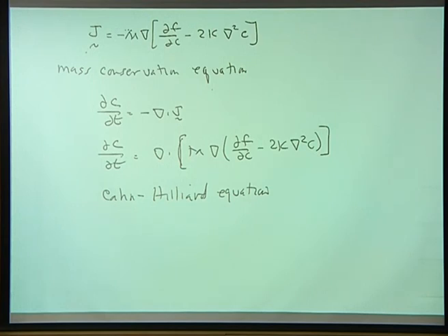So it involves the compositions that you get from the free energies. And here's the connection to thermodynamics. I give you a free energy function. It can be something that you get from a CALPHAD fit, for example. A CALPHAD free energy function is a function of composition for a particular system of interest. And if you know what the gradient energy coefficient is, you just have to take the Laplacian of the concentration field and you get the flux. Okay? Tomorrow we'll be talking a lot about this equation because it is the basic model. If you look at any phase field model, it starts with one of these Cahn-Hilliard-like equations. Okay, questions? Oh, the interaction range?